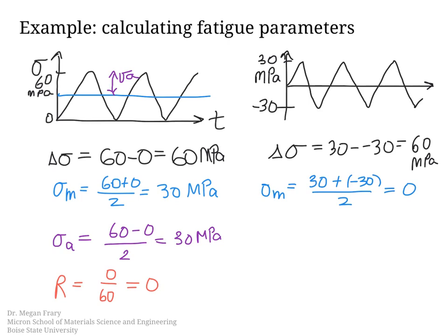Let's find the mean stress next. In this case, though, the mean stress we find is equal to 0, and we see that right here on the stress axis. Now let's look at the stress amplitude. As in the first example, we find again that the stress amplitude is equal to 30. And so these have the same stress range and the same stress amplitude, although they have a different mean stress. The mean stress was higher in the first case.